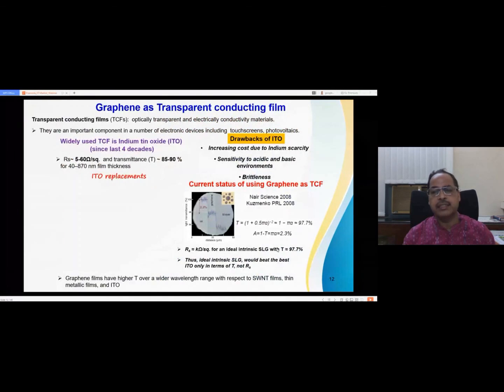Then you characterize using mostly Raman spectroscopy to find whether it is single layer or multi-layer graphene. Then you proceed to its application. So one of the applications here I am showing is graphene as a transparent conducting film. When you talk about transparent conducting film, it should be an optically transparent and electrically conductive material. These are important components of electronic devices such as touch screens and photovoltaics. The most widely used transparent conducting film is indium tin oxide.